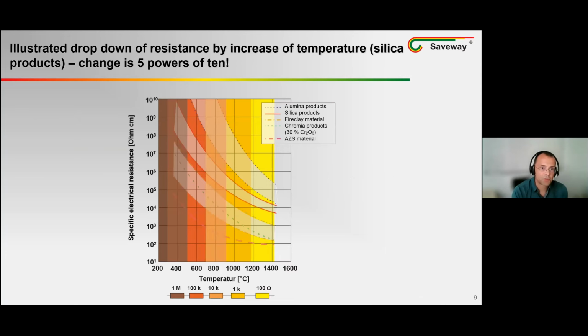The graph illustrates the significant decrease in the electrical resistance of the lining with increasing temperature. For visual clarity, the colder temperatures are underlaid with darker colors. Here in the graph, we use the different colors to illustrate temperature ranges to which we subsequently add values for electrical resistance. The change is 5 powers of 10.